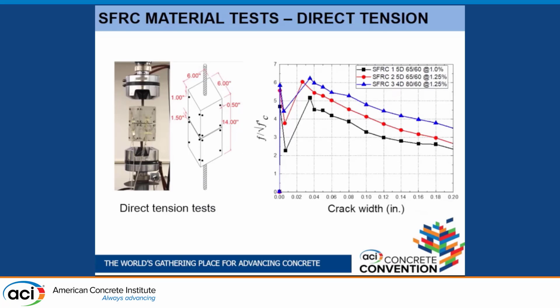We also did some material tests to evaluate the performance of the materials. One of those tests was a direct tension test of notched specimens. Of interest here is the tensile stress versus crack width obtained for these prisms under direct tension, which were notched. This is normalized by square root of f prime c.